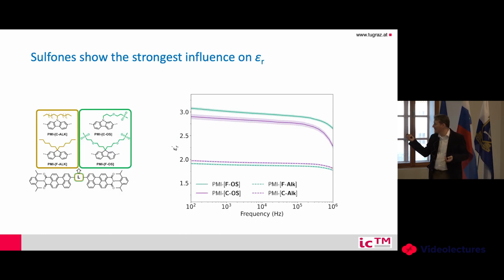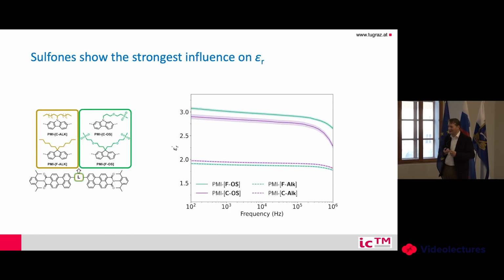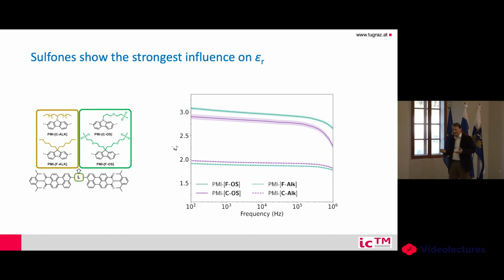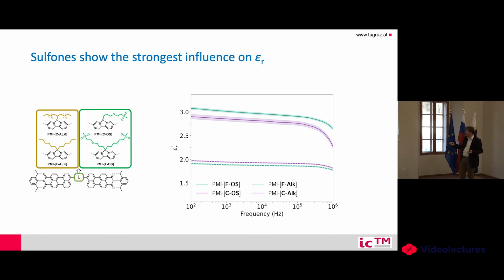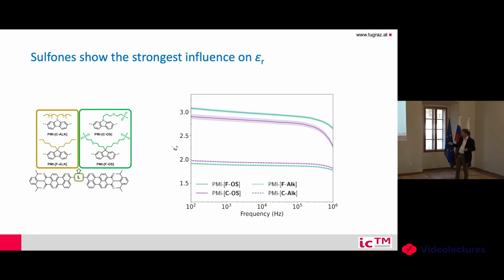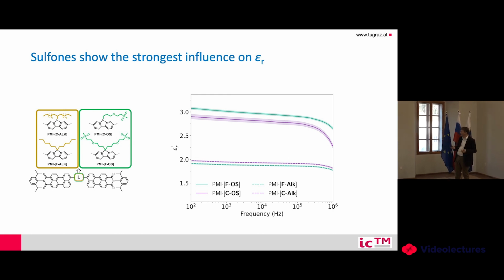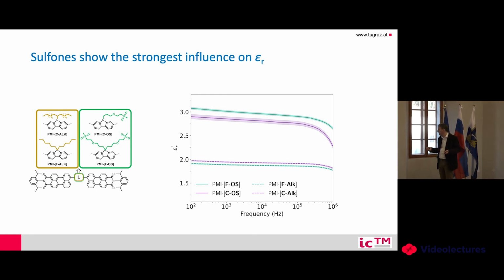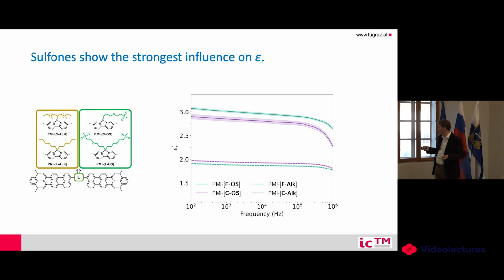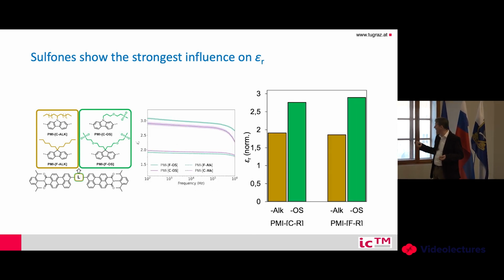Then of course in our case we have to prove that the permittivity is really larger, because this was our idea. This is a comparison of these two materials with the pure alkyl side chain. So this is the original value, and you see in both cases we get a strong increase of the permittivity of more than 50%. So actually the material is as expected.